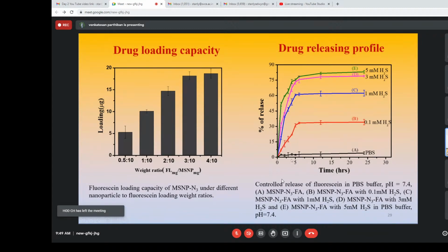In the drug release experiment, initially in PBS there is no drug leakage. In some papers, maybe 10% of the drug will be released initially within 1 hour, so a burst release is possible. But in our case, for up to 1 day, 24 hours, there is no drug leakage. After that, we slowly increase the H2S concentration. We can see that up to a 5 millimolar concentration, within 5 hours, almost 75% of the drug will be released.